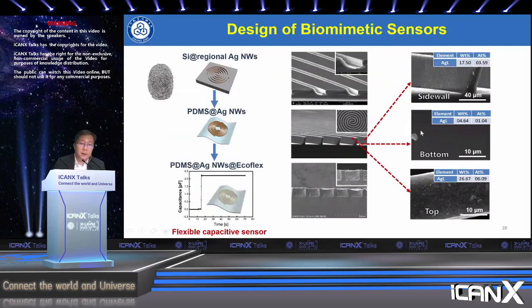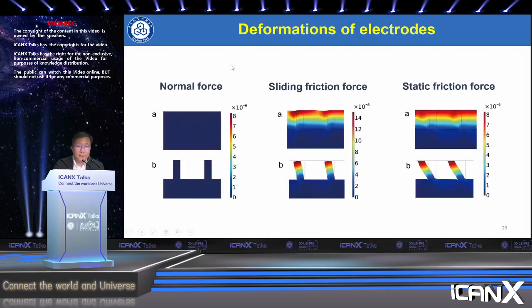This is the design and the fabrication of our device. From here, you can see that the silver nanowires were spray coated onto the silicon wafer mold, and then the silver nanowires on the top layer of the silicon mold were removed. Through the replication process, the silver nanowires were embedded on the surface of the 3D PDMS microcolumns, and there are no silver nanowires existing between the microcolumns. And finally, the silicone rubber Ecoflex was used as a dielectric to fill the grooves between the microcolumns to make this device.